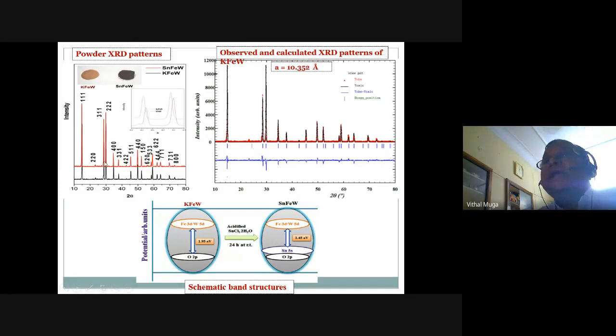But when you expand this portion in an expanded scale, you will see that there is a shift in the D lines. This shift in the D lines will be sufficient for us to conclude that tin has gone into the place of potassium. Now why does this occur? This is a specific structure which permits ion exchange. We have done this Rietveld analysis. Don't worry about this, because journals ask you to do Rietveld analysis and confirm everything. One need not worry about that, but worry about this color and the powder XRD, how it changes.